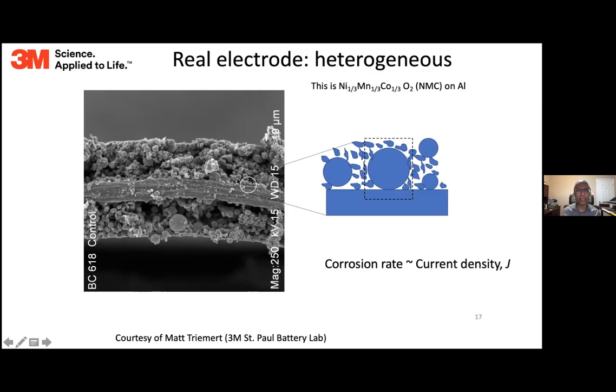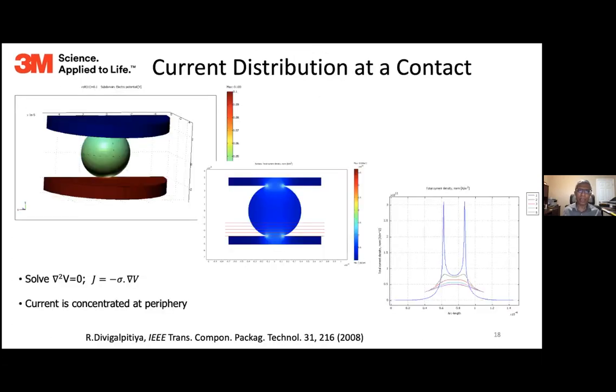So you have spherical particles making contact with the planar aluminum. In device operation, what you are interested in is the corrosion rate; we want to minimize that. What happens at the interface is the most important. Corrosion rate, if you think in terms of the Faraday picture, is basically the rate of electron transfer, which in physicist terms is the current density. So the corrosion rate is proportional to the current density at the interface, right? Let's digress a little bit and look at the current density at any contact.